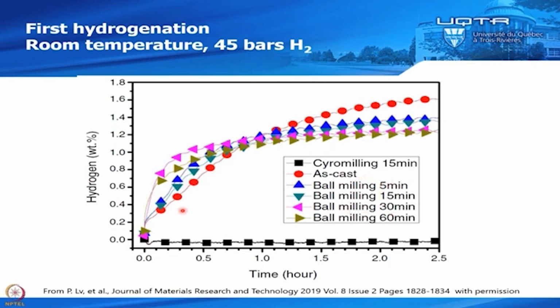But for milling at room temperature, you see that this is 5 minutes and 15 minutes, 30 minutes, and 60 minutes. And you see that as the milling time is getting bigger, the kinetic is getting faster. So you have a faster kinetic, longer milling time gives you faster kinetic, but you see that the capacity is getting down. So kinetic is getting better, but capacity is getting worse. So how could you explain that?